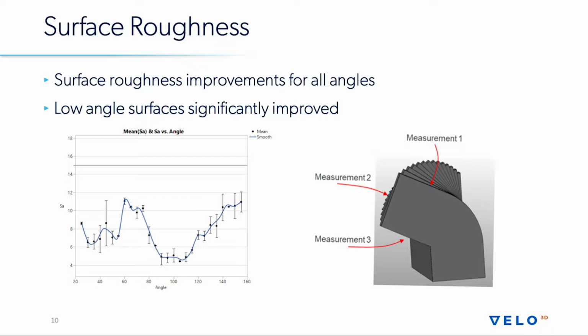In addition to static mechanicals, one of the things that people always ask about is surface finish, especially with 3D printed parts. And another thing that drives me crazy about a lot of the material data sheets that you'll get is the surface finish callout will say 6 micron Ra. And it's like, where? On what part of the part are you getting 6 micron Ra? Is it everywhere? Is it every surface? What angle is it at? What's your variation? So we wanted to give an idea with a base parameter set.